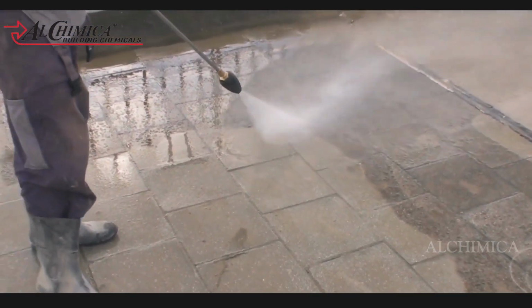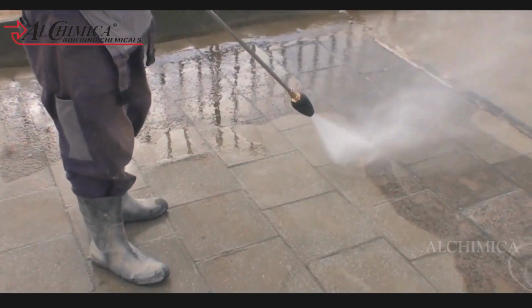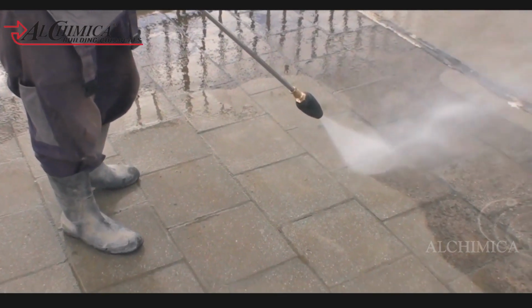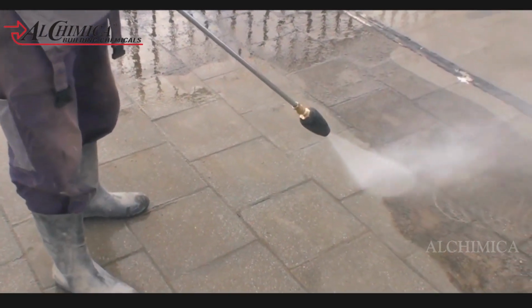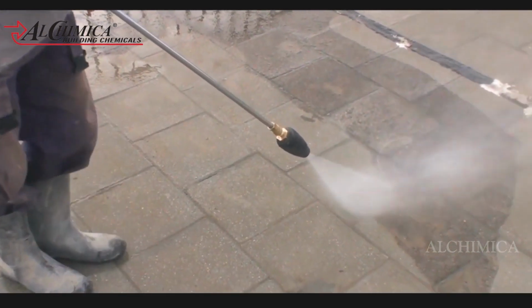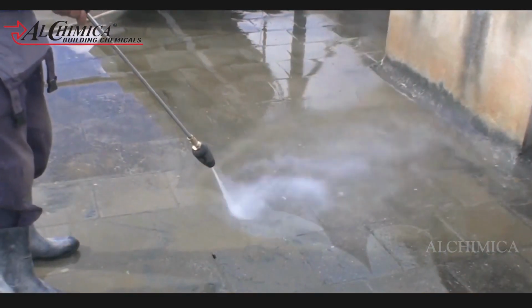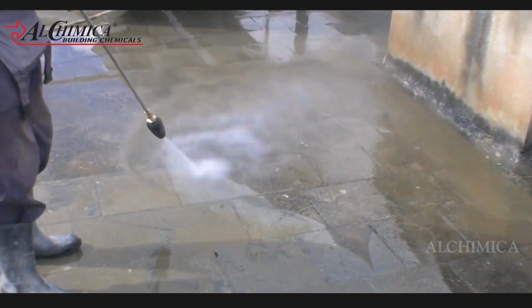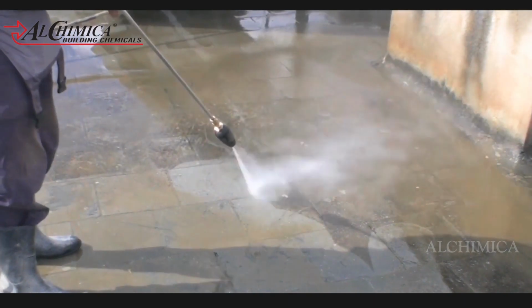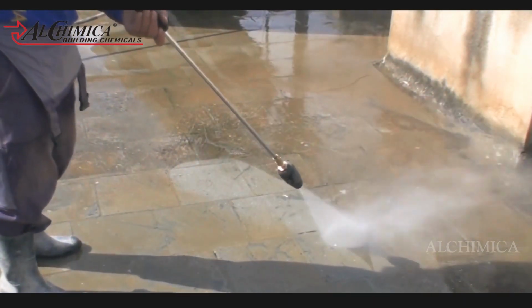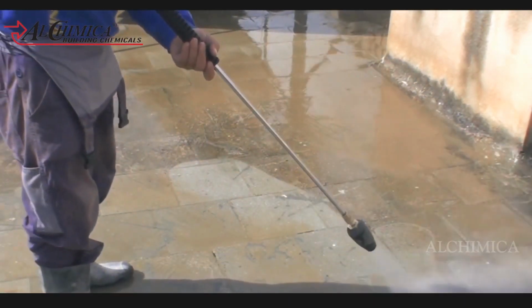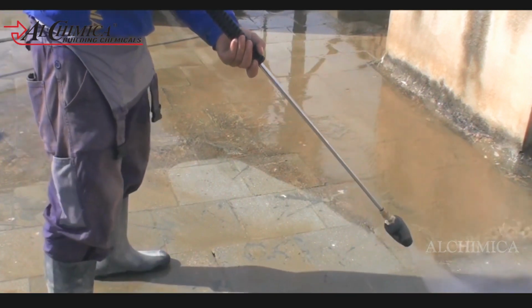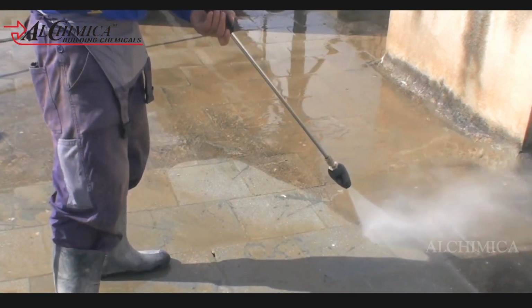Based on the condition of the terrace, the surface is cleaned with either a wire brush, a buffing machine, or a water jet, to remove all kinds of contaminations like oil, paint, grease, curing compound, dead mortar or other loose materials from the surface. It is advisable to wash the surface with clean water to remove all dust from the surface.